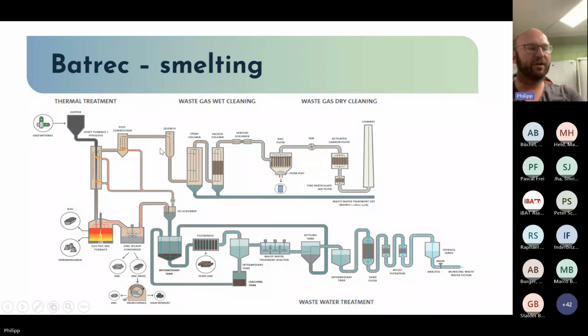So for our output fractions, we have some filter dust here. We have slag, which has to be deposited at the moment because in Switzerland it's not allowed to use this slag, for example, as construction material. But there we are looking for outlets, maybe in Europe. Our ferromanganese. This is something, for example, for foundries or steel manufacturer. Then we can recover metallic zinc, and we have some skimmings here. And because of the process, 1/3 of these skimmings is metallic zinc, and this is something we can remelt here to increase our recovery rate of zinc. So, and then these skimmings are going to another recycler to remove the rest of zinc from this material.